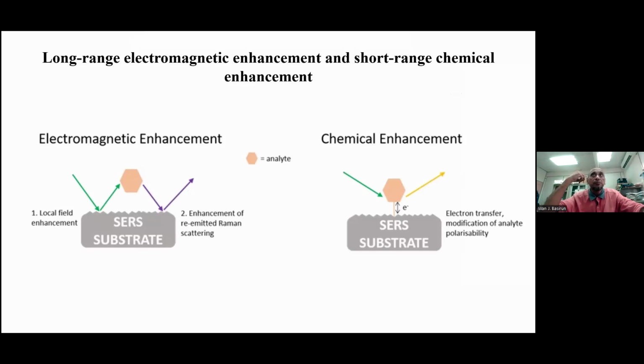So electromagnetic enhancement happens due to the irradiation of the laser onto the substrate, which promotes plasmonic resonance, and this plasmonic resonance will irradiate a secondary radiation, or scatter a second radiation. That radiation is what is detected by the Raman detector. So this is known as electromagnetic enhancement. This electromagnetic enhancement is a long range enhancement, while chemical enhancement is a short range enhancement.